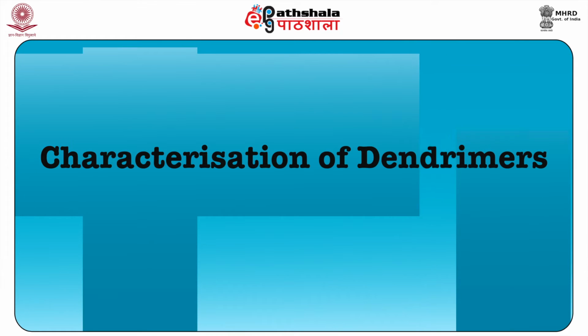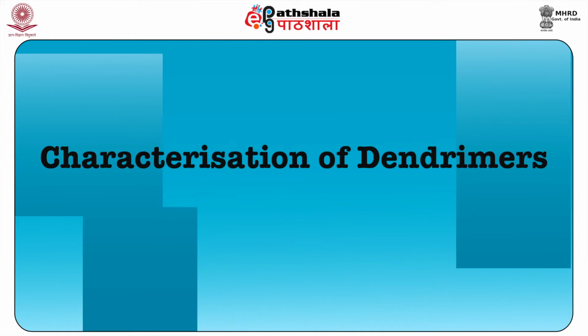Now coming down to the topic of characterization of dendrimers, after having studied the synthesis of dendrimers. It is tough to determine the purity of a dendrimer, that is the percentage of defect-free dendrimer, due to their large size and high symmetry. Various characterization techniques such as elemental analysis, chromatography, specifically HPLC, and NMR spectroscopy are used, but small amounts of impurities are generally not exposed in higher generation dendrimers.